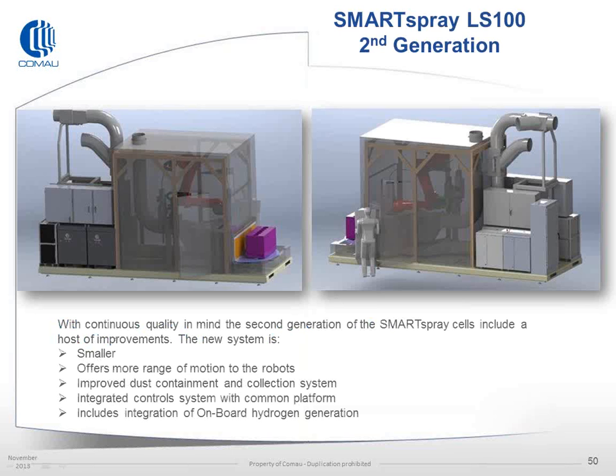So our second generation, which we were already in the process of producing here, has gone to adding a larger table to accommodate some significantly sized blocks. We've also reduced the size of the power supply when we use an 85 amp system. But one of the more significant changes is that we've added the ability to produce hydrogen on board. The reason for this is the regulations around pressurized hydrogen. It's much simpler for us to provide hydrogen on demand to the cell and be well below any requirements for permitting. It makes it a much simpler system and allows us to provide a simple package to a customer without a large impact to their manufacturing facility.